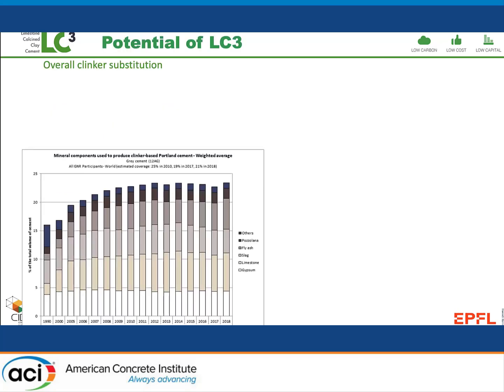What I'm more interested in is what it can do on a worldwide basis, because that's what we're really confronting with this climate crisis here. And here we see the average level of cement substitution amongst the companies who are members of the Global Cement and Concrete Association. And we see that in the last 10 years, this level of substitution has stagnated at around 20%, because it takes also account of the 5% gypsum here.